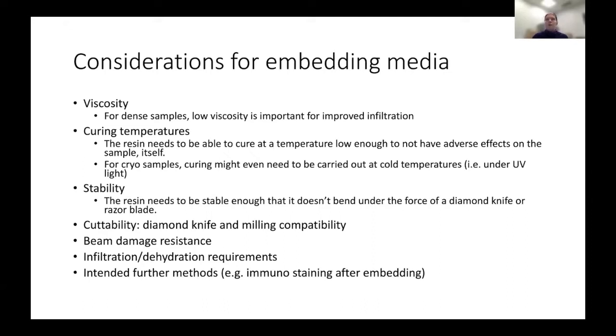There is some recent information based on ion sources and milling showing that different resins have different compatibilities. So you want to be careful and select a resin that is compatible with either your ion source if you're milling or a diamond knife. Most resins are compatible with a diamond knife, but not all of them. Some of them can chemically attack diamond or glass. Beam damage resistance is always good, something to keep in mind. If your sample is not dense and it can withstand any temperature and it's already plenty stable, you just want to take sections from it and you need to embed it in resin, I recommend then opting for a resin that has a lot of beam damage resistance.